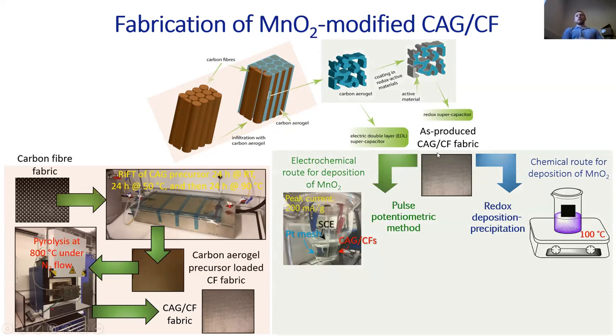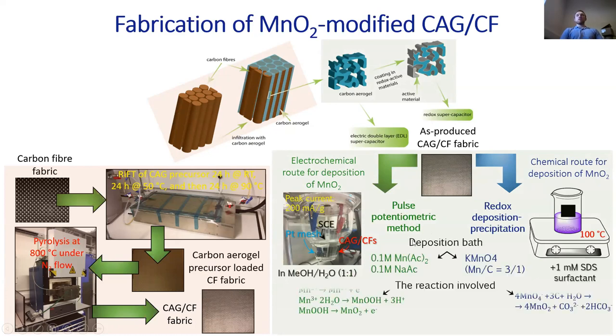The deposition of manganese oxide was performed in two different routes. In the first one, the electrochemical route, the pulse potentiometric method was applied. This involves oxidation of manganese 2+ precursor species in the 3-electrode electrochemical cell, where our carbon fiber electrode serves as the working electrode. And manganese 2+ species undergo different steps through hydrolysis and oxidation, forming manganese oxide inside of our pores. The other route is the chemical redox deposition precipitation at high temperature, where permanganate ions get reduced on the surface of carbon inside of the carbon aerogel pores, forming manganese oxide.